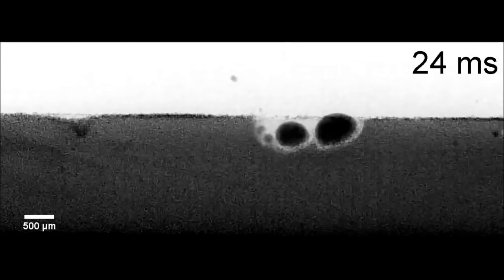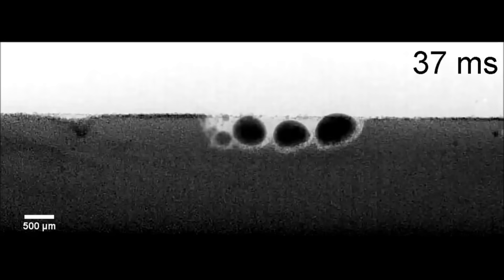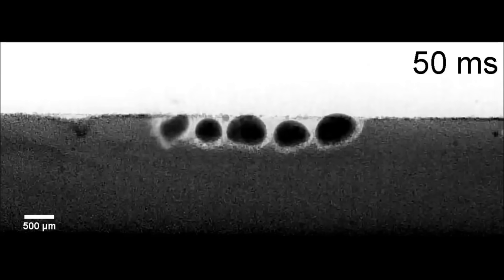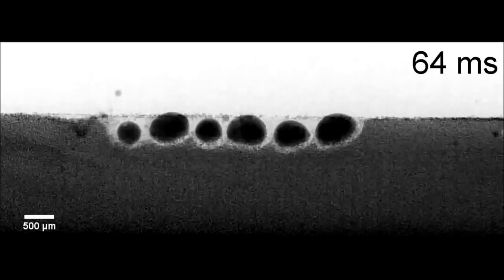Finally, we see some worrisome behaviour as the laser reaches the end of this track. As the molten metal begins to cool, we see pores begin to form in the upper surface of the track. The exact kind of imperfections that could allow crack growth to occur in the future. This study also varied several factors like laser speed and laser power to study their effects on the melt tracks properties. Here they increased the speed of the laser to a point where the metal particles did not have enough time to heat up and coalesce.